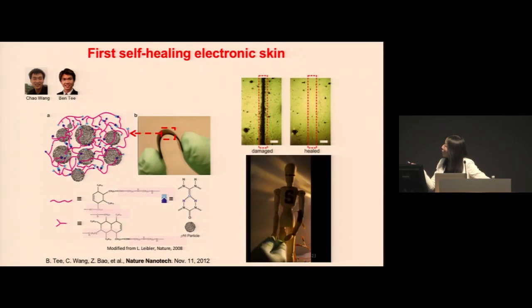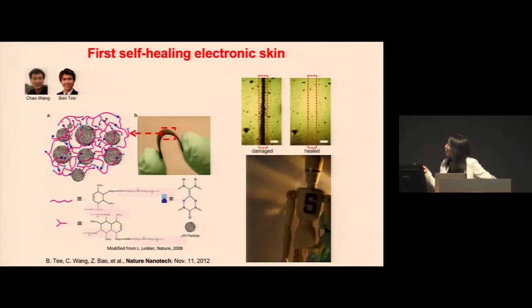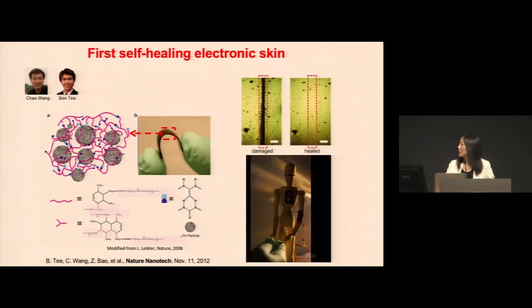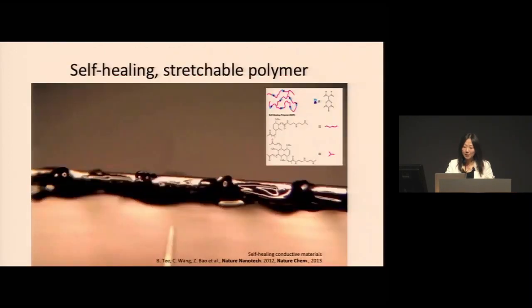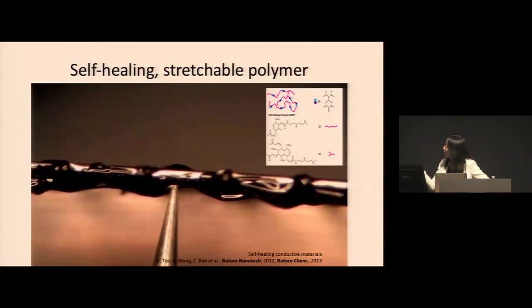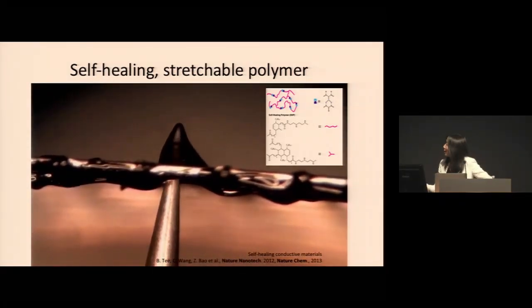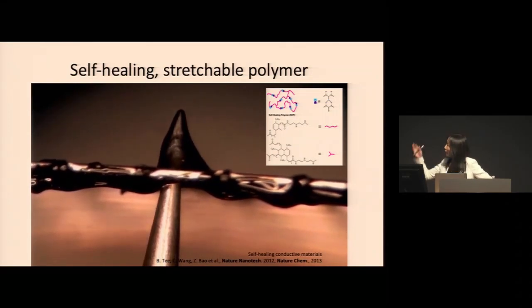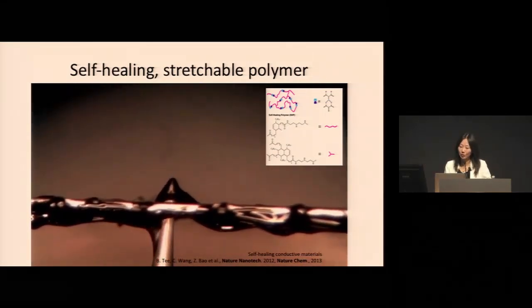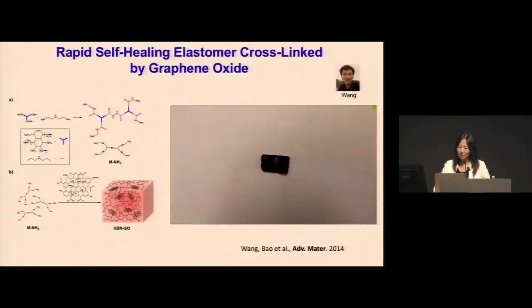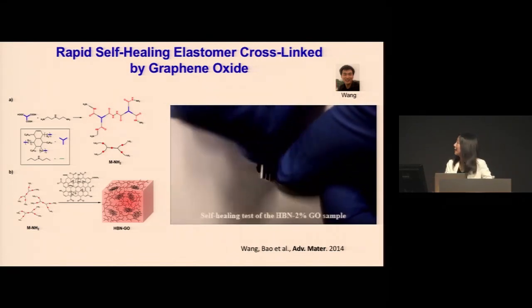And to make an electronic skin, we incorporated nanostructured conductive particles to allow the material to not only self-heal, but also be able to sense pressure and sense strain. That's why we call it the first self-healable electronic skin. But one issue with this material is that even though it self-heals, it's highly viscoelastic. It is able to tolerate extremely high strain, but it takes a while for the polymer to return to its original shape. So in other words, we need a material that's also highly elastic.